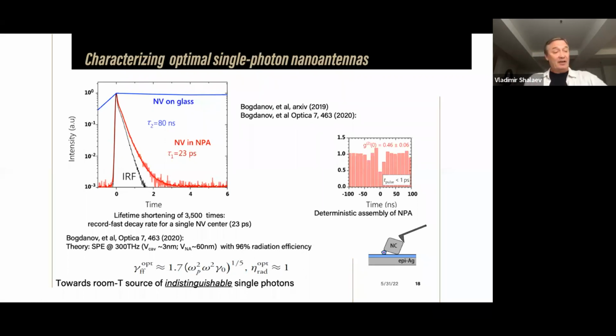So that's quite impressive. And in principle, in this particular case, even this enhancement we obtained is not sufficient, because the dephasing time is even shorter in the case of nitrogen vacancies, because of very strong coupling to phonons. So we actually need to get a system with a relatively low decoherence time, let's say around a picosecond.